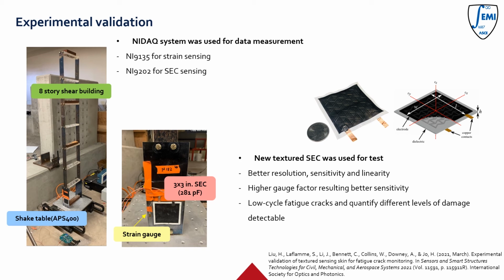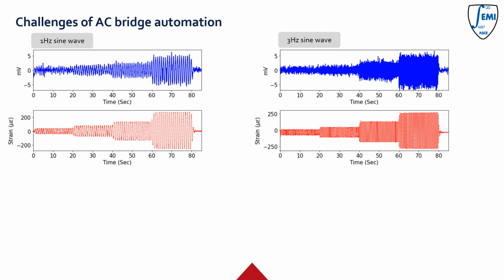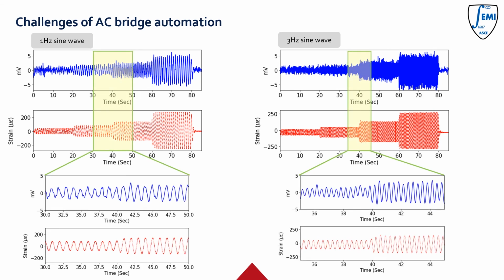A steel plate specimen was fabricated using the new textured SEC and strain sensor shown in the figure. We tested 1 Hz and 3 Hz cyclic sine excitation. The test was conducted after the automated balancing, amplification, and shunt calibration. The sensor board was able to measure the dynamics with amplitude variation very well.